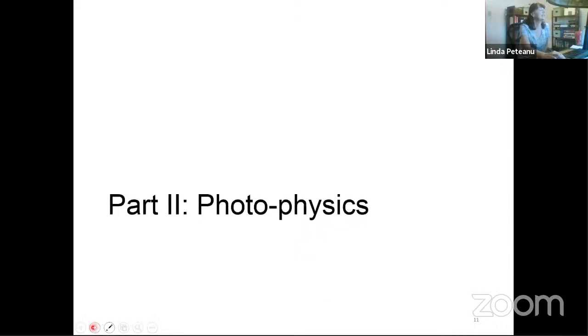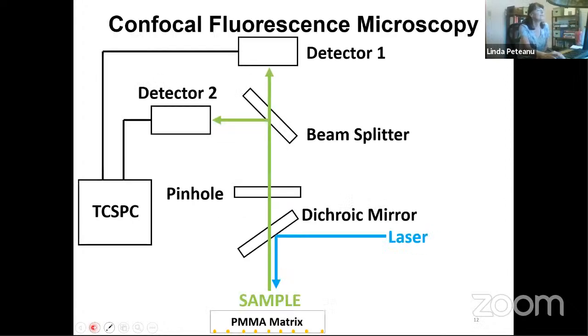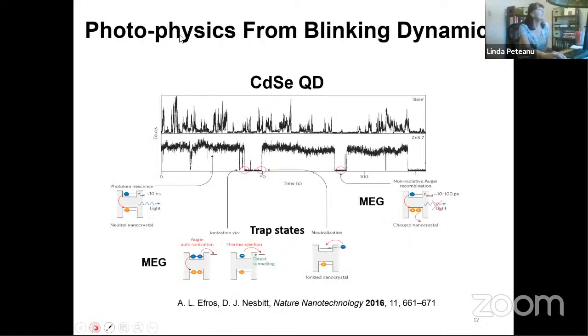Turning now to the photophysics of these systems, what I'm going to tell you now has primarily been done using confocal fluorescence microscopy, either in solution or as shown here in a PMMA matrix, basically a microscope. It's exciting the sample, collecting the emission, splitting it between two detectors, and you can do both steady state and time correlated single photon counting in these systems. So what has been done in the case of, let's say, cadmium selenide quantum dots as an example, if you look at a single quantum dot, you see what's known as intermittent emission. So you get bursts of emission and then quiescent zones and bursts and so forth.